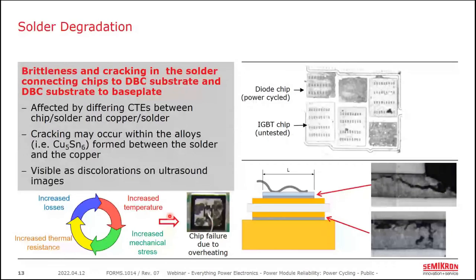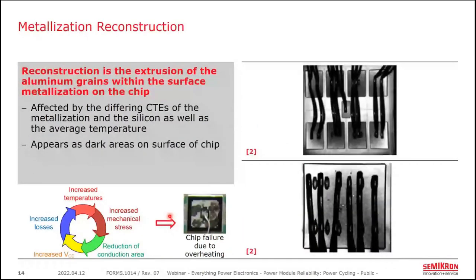So slightly less common than the last two failure modes is what we call metallization reconstruction, which occurs in the top of the semiconductor chip where there's that thin layer of aluminum. So power cycling, particularly where high currents occur, and high currents means above the surge current rating of the device, can cause the individual aluminum grains in the metallization to extrude. And bear in mind that silicon and aluminum have two very different coefficients of thermal expansion. So there's a lot of thermal mechanical stress at that interface.